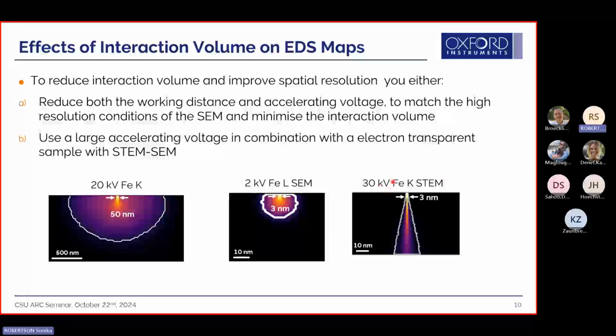And then this is the 30 kV STEM example. If you see, this is not to scale. Don't compare those things. The 10 nanometer part is right. But again, because the sample is so thin, it doesn't get enough time to spread in volume. And that's what's helping improve your spatial resolution with the probe current, the smaller probe current.